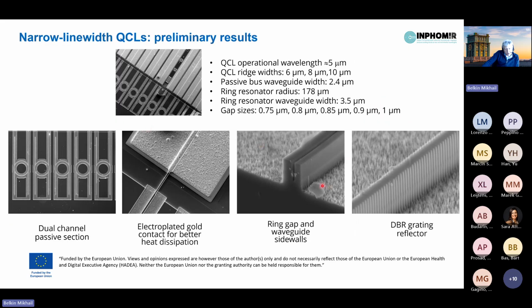Implementation is still ongoing. These are some of the PICs that we have fabricated recently. Fabrication was not exactly perfect. As you may see, there was some problem with the etching. But what you see here is the PIC itself. This is the laser. This is the bus waveguide to which the laser is coupled. This is the ring resonator, and this is the DBR section. So light goes from the laser into the passive, coupled to the ring, coupled to the drop waveguide, reflected off by the DBR section, and is coupled back to the laser.